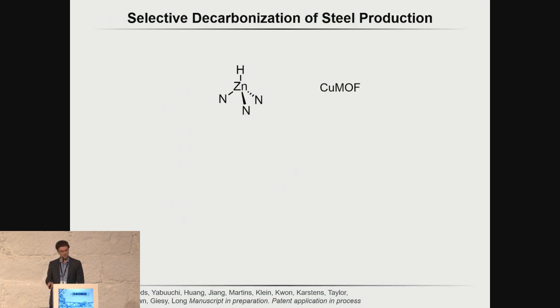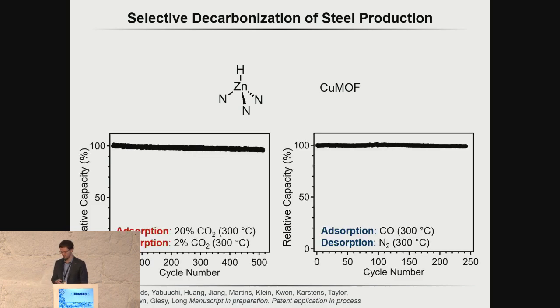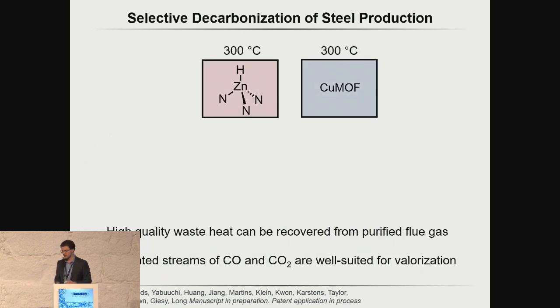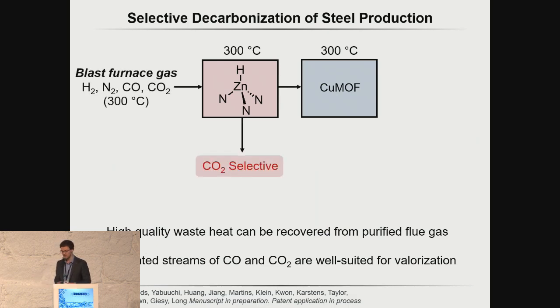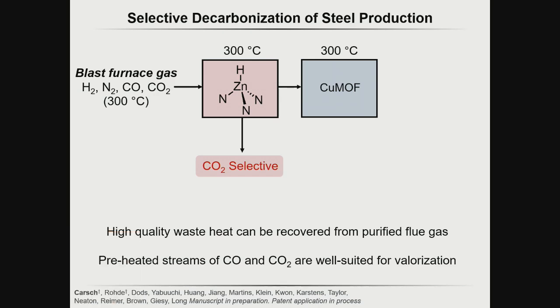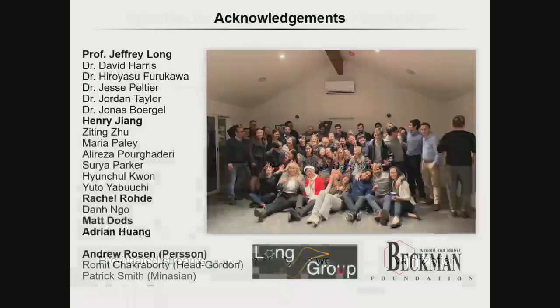So let's put these two frameworks together, our metal hydride and this copper-1 metal organic framework. We can cycle these using thermogravimetric analysis measurements where we can load the gas and then unload the gas. And then we compare these together to what's being considered a dream reaction or a dream separation, where you can take something like blast furnace gas at elevated temperatures, and without having to undergo complicated transfer of heat, we can simply strip out the carbon dioxide, the carbon monoxide, and then undergo subsequent valorization of these chemicals, where we've been able to retain that heat energy for subsequent processes.